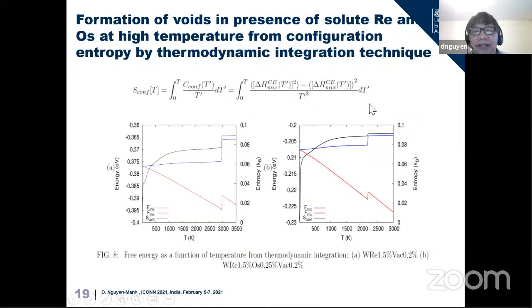Because we're looking at thermodynamics under irradiation, we see that the formation of void can be understood from the free energy calculation. For example, here is showing the configurational entropy calculated from this formulation, and we see that at high temperature from this ordered configuration, there is a jump in entropy in both tungsten, rhenium, vacancy and tungsten, osmium, rhenium, vacancy. So there is a jump in entropy, which is what happens at high temperature to form the void in tungsten, and it is what we see in the simulation here.